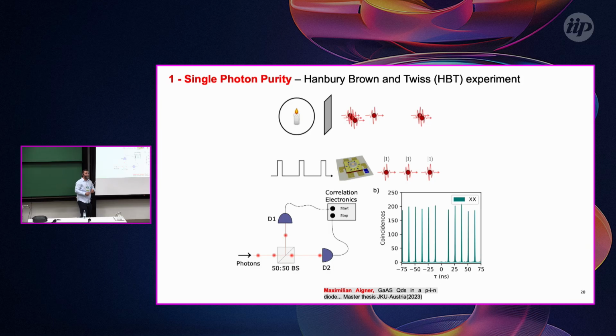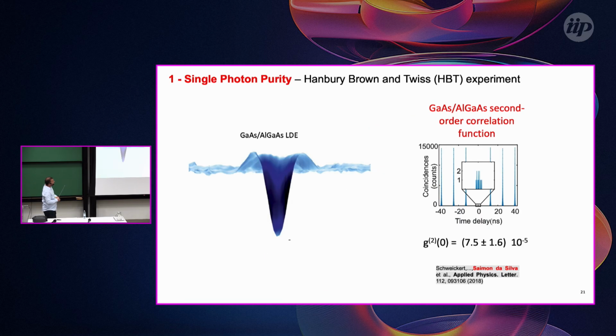Basically, what we are looking at here is the probability that at zero time delay, one photon reaches the detector. If this is a real single photon source, only one photon will reach the detector. You will not see a correlation at this zero time delay. In 2018, we grew one kind of gallium arsenide quantum dot, and we demonstrated that this g2 is around 10 to the minus 5. This is one of the best values that you can find among solid state sources. This means that we don't have much probability of getting two photons when you press a button if you make a device with these gallium arsenide quantum dots.